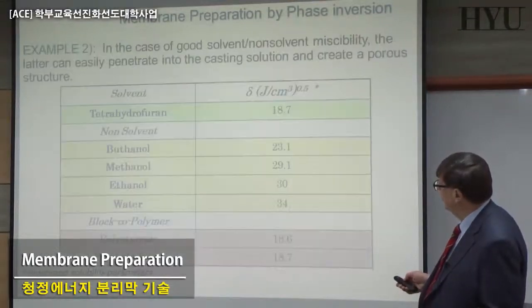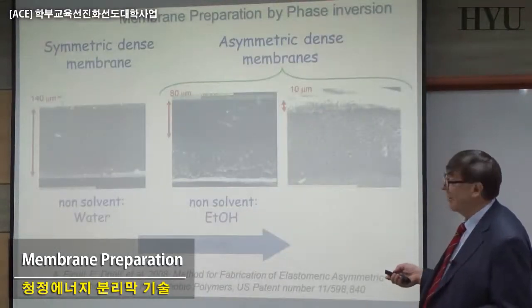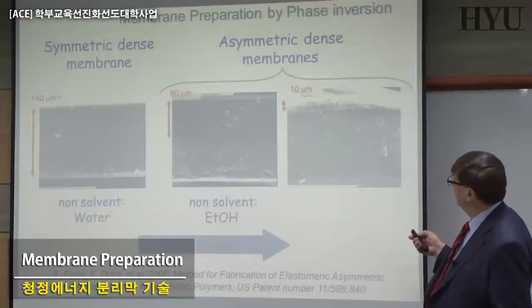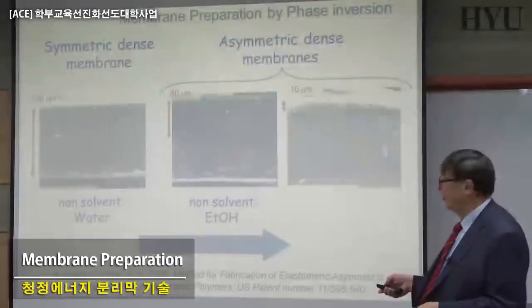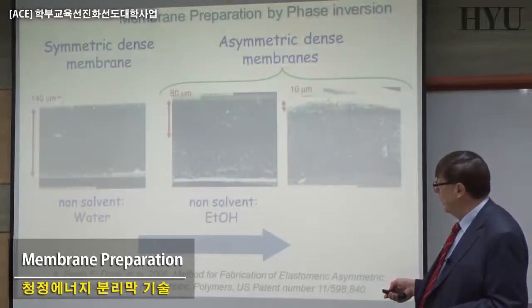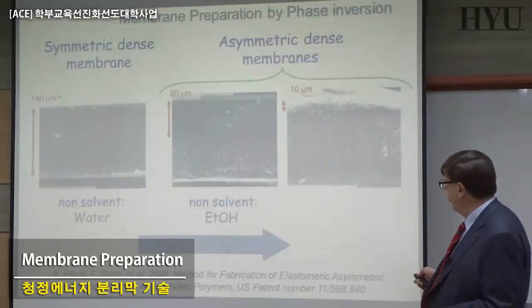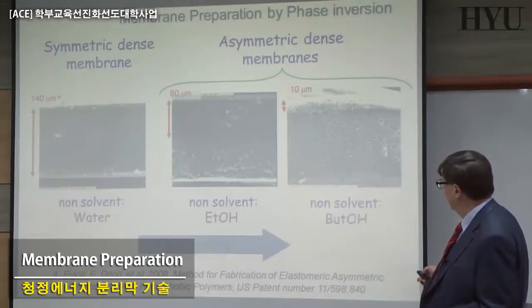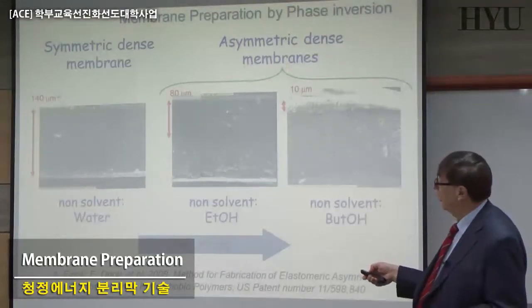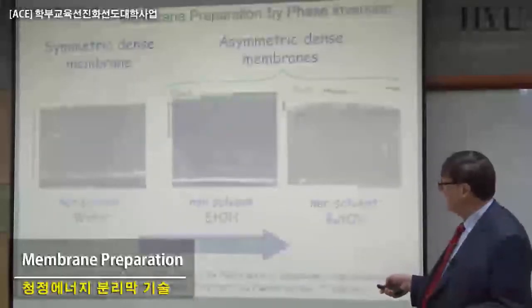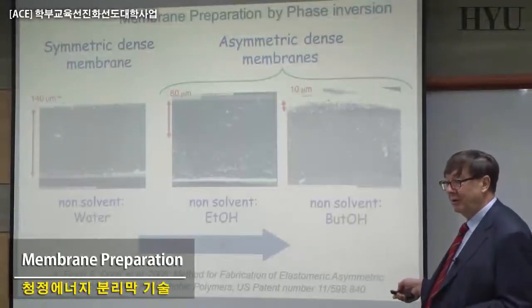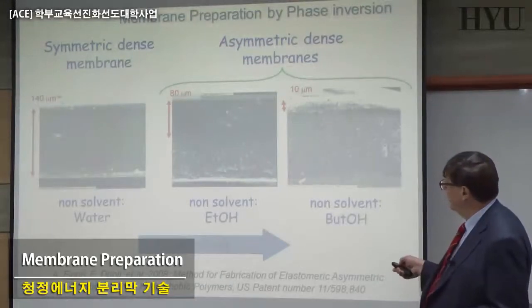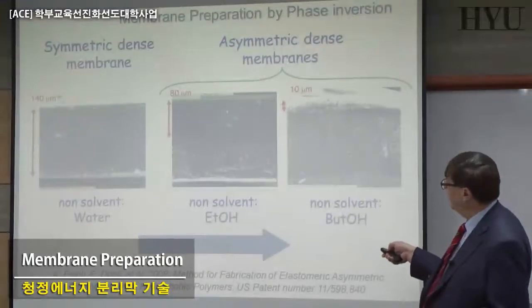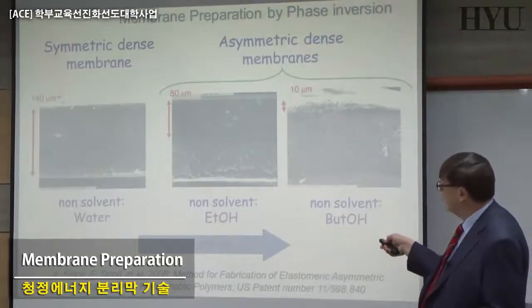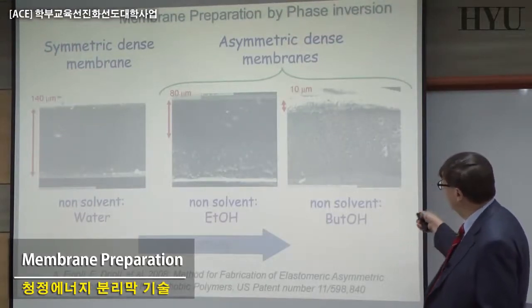Just to show you how significant the effect can be. With the same kind of membranes, changing the non-solvent from water to ethanol or butanol, you can go from a dense membrane at the end, just using water, to inducing porosity if you increase the affinity with ethanol or butanol, and that is asymmetric with a layer. You can change the thickness of the dense layer, and at the end it can be totally porous.